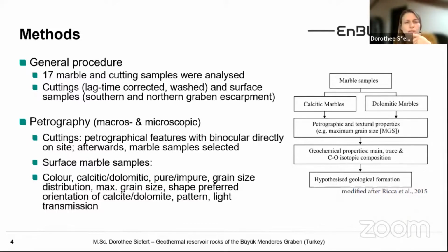So we took this approach from Ricca et al., which was originally called the provenance determination key, and modified it a bit. So after sampling, the marbles are classified as pure or impure, calcitic or dolomitic, and here we applied an approach by Rosen, where a pure calcitic marble is characterized by a modal calcite content of higher than 95%,